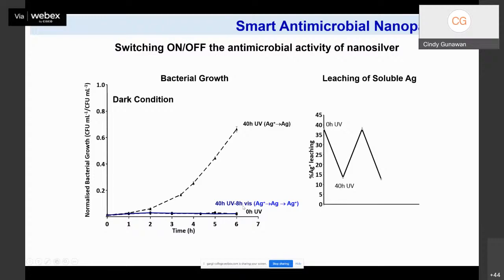If you remember from the scheme, with the UVA illumination, the silver ion has been reduced to metallic silver. Because it has been reduced to metallic silver, these nanoparticles are responsive to visible light because of their surface plasmon resonance. Therefore, when we expose these nanoparticles to visible light, the metallic silver deposit will be oxidized back to silver 1. And when we test with the bacteria, we can see that the growth is inhibited again. It means that the antimicrobial activity is switched on.